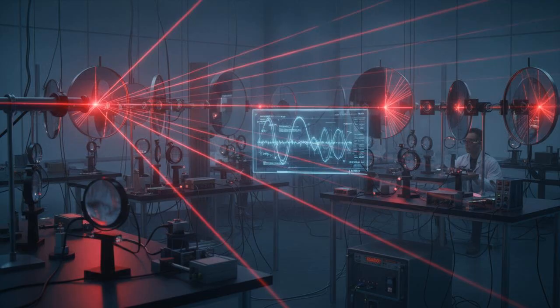electrical current being generated. Another vital tool is time-resolved terahertz spectroscopy. Terahertz radiation is exquisitely sensitive to the motion of free charges, allowing scientists to watch polaron dynamics in real time. By measuring the complex optical conductivity of a material just picoseconds after photoexcitation, terahertz pulses map the mobility and delocalization of the charges, proving that minimizing trap states is the ultimate key to extracting these charges before they are lost.